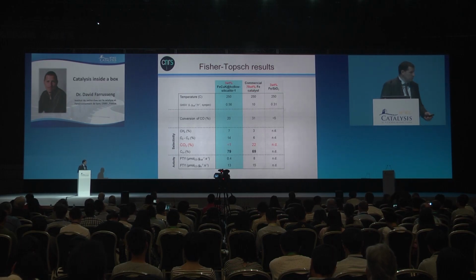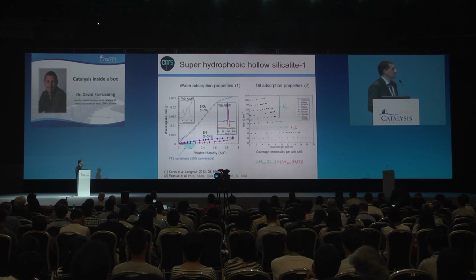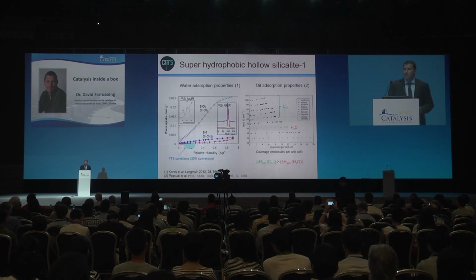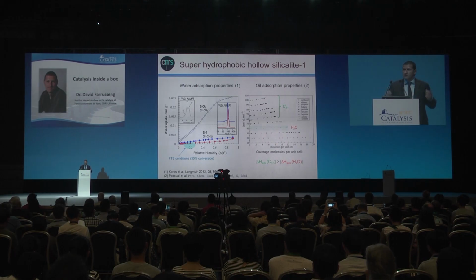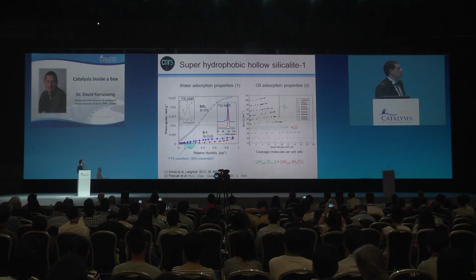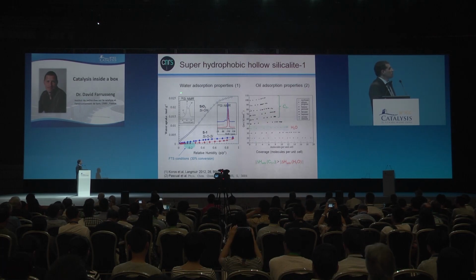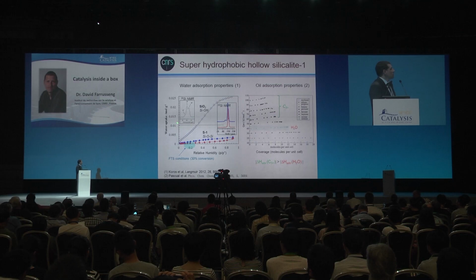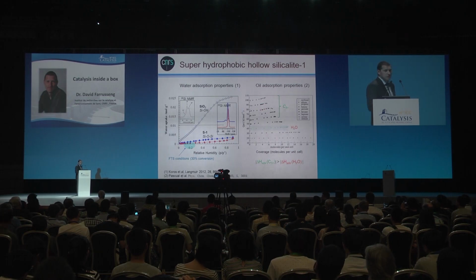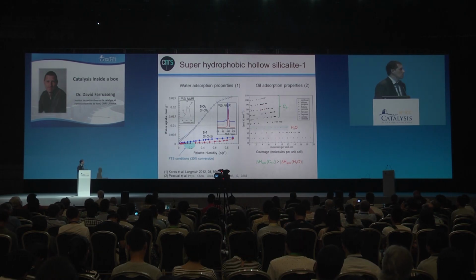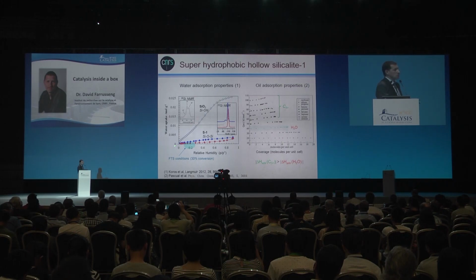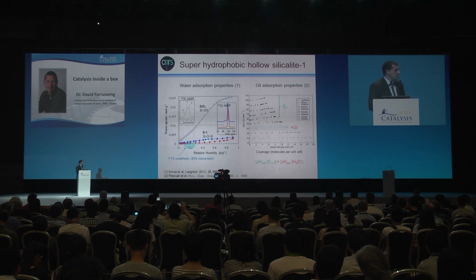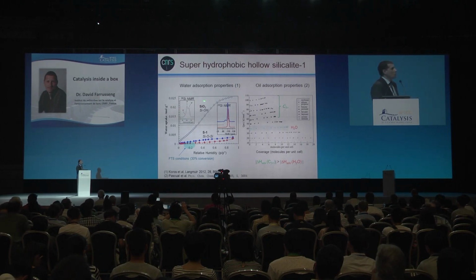So we were wondering why we have such selectivity, and it comes from the adsorption property of the zeolite, of the matrix in which the iron nanoparticle is embedded. Here are the water adsorption properties, you can see the water uptake as a function of the relative humidity. If you take a silicate, whatever it is, it has a lot of silanol groups at the surface, which make it very hydrophilic. You adsorb a lot of water, whatever the relative humidity. In NMR, it is known as Q2 or Q3.